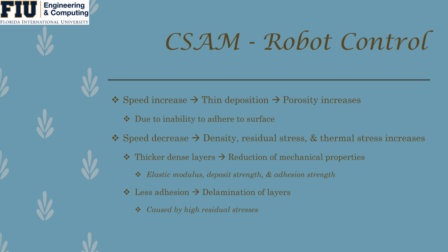One of these mechanical properties that's very important is the adhesion strength. Having less adhesion allows for the delamination of layers, which is caused by the high residual stresses. The reason why we also have an increase of thermal stresses, even though we're not melting the particles, is due to the localized particle deposition, which is at the same location because it's moving very slow, allowing for that area to increase in temperature.